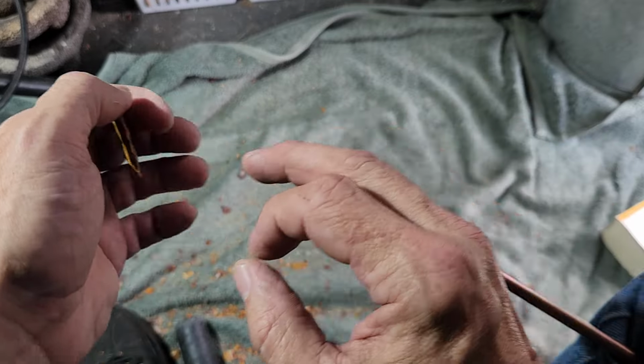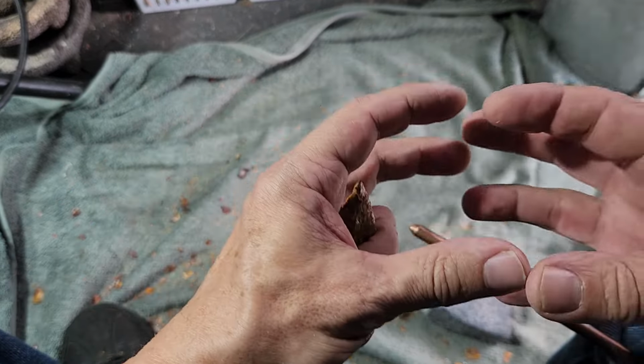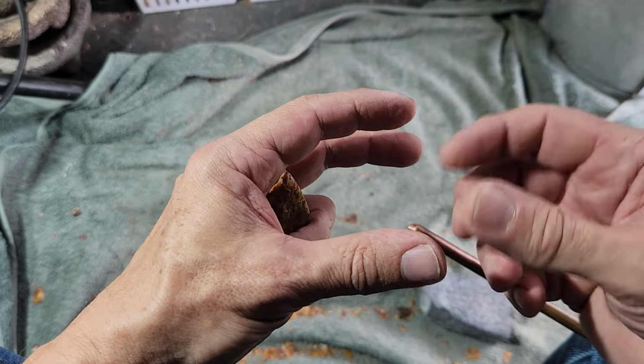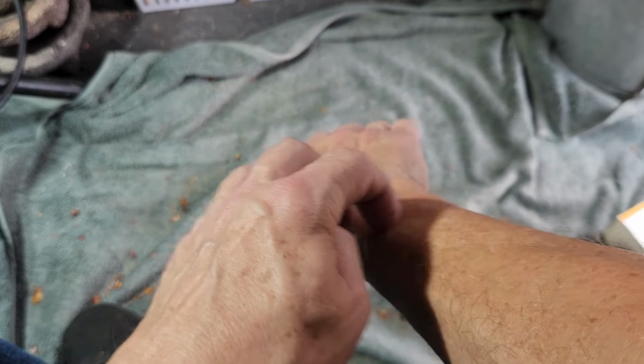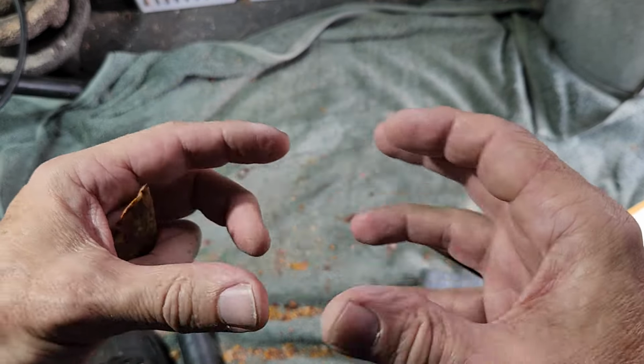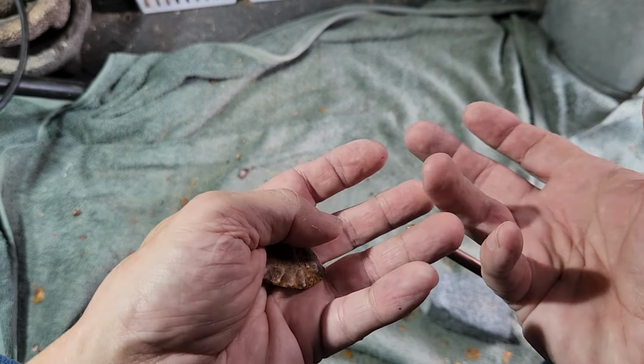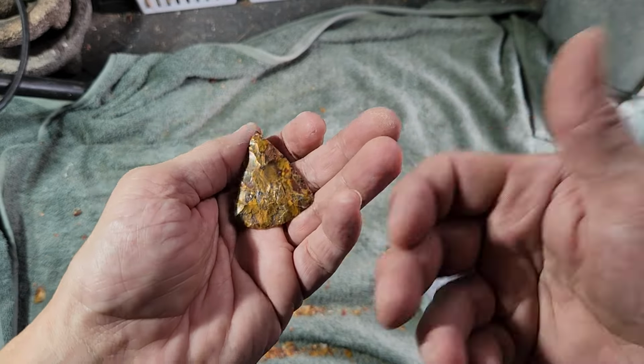yeah, this one broke up and the other ones are fine. I got three over here that on the first heat treat reacted really well, and then I tried it again, and two of these three broke up. Or this first batch heated well, but I took another batch of six and compared it with the three flakes and it didn't do anything. The heat treat at the same temperature didn't knap any better. You'll find variation in your experiments.